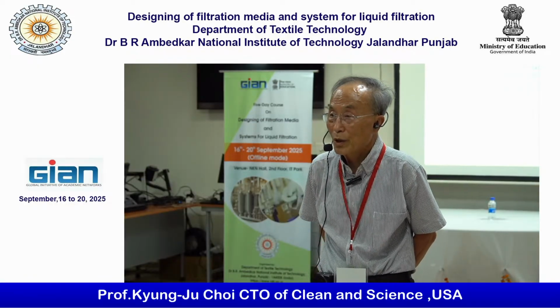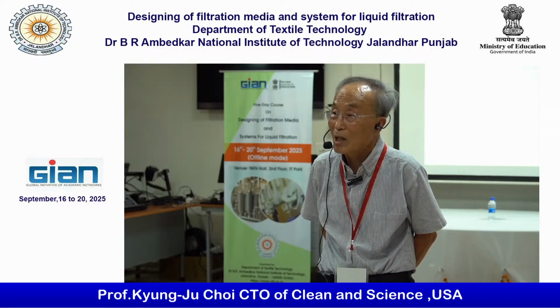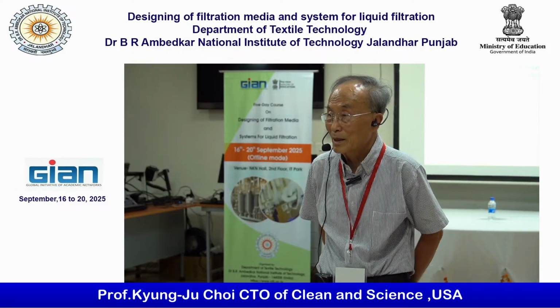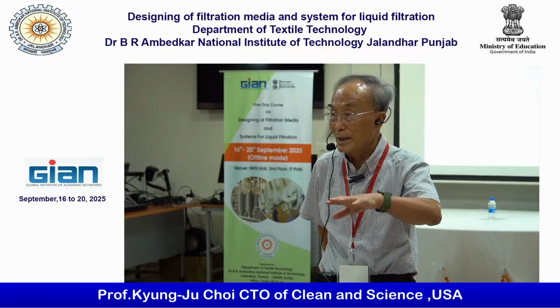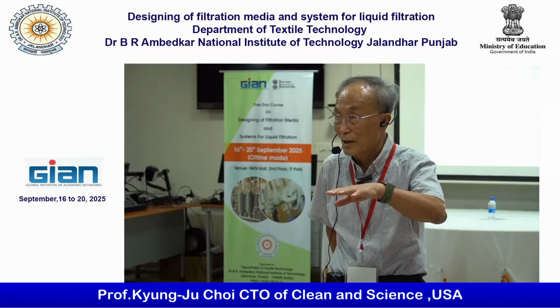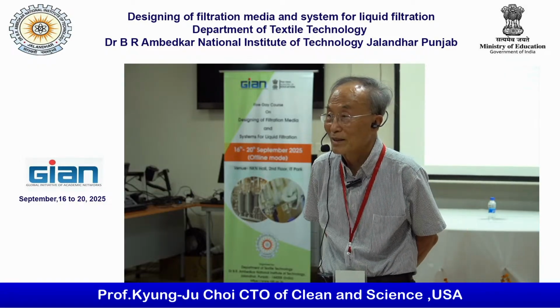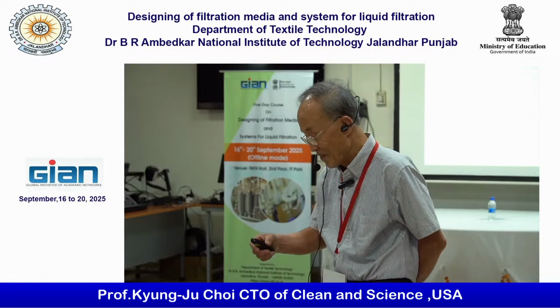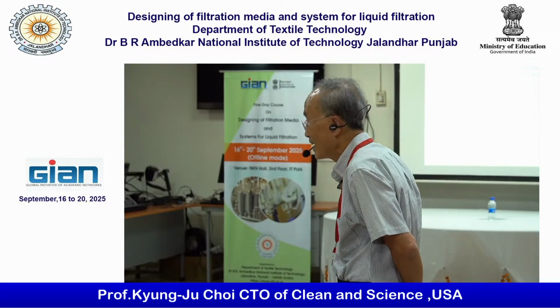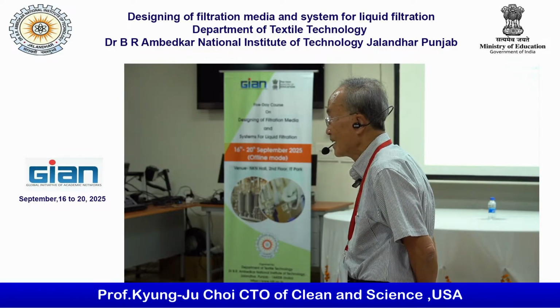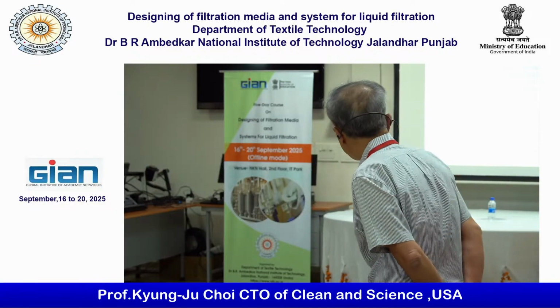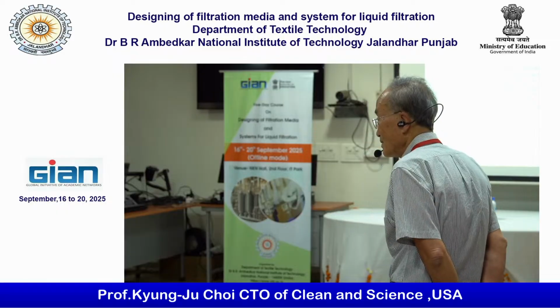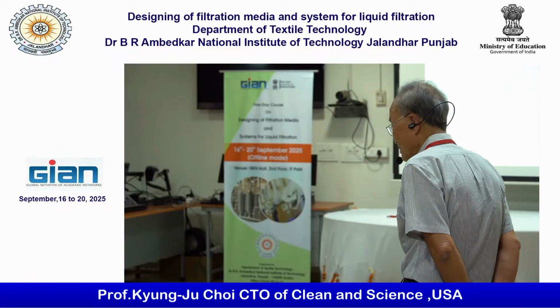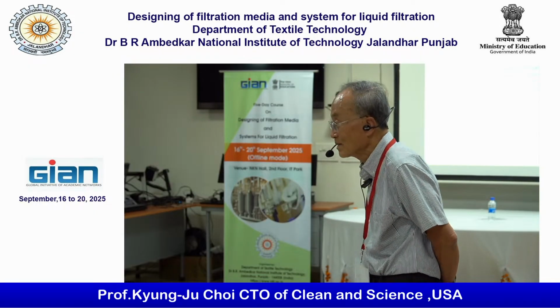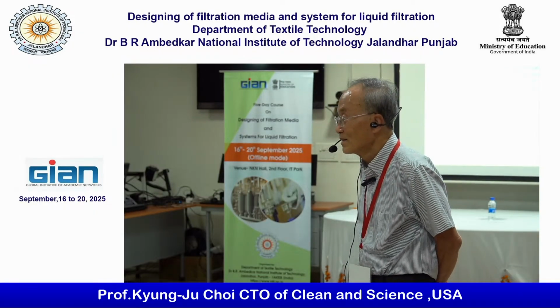However, when you handle it, you're going to lose a lot of water out of the media itself. It's not going to stay long enough. I hope you understand. Another point is that with water, you have to see whether the fiber swells. If there is swelling, then obviously the porous structure will change. During the measurement, that also should be taken care of. If you are testing polyester, it will not swell. If you are going for cotton fiber, it will swell. That void will change.